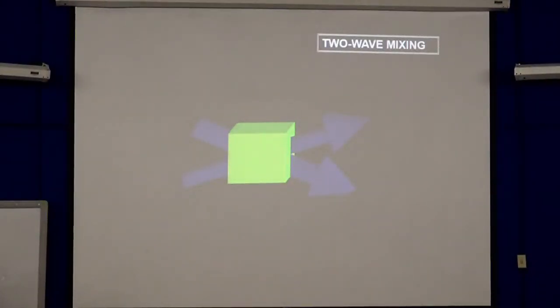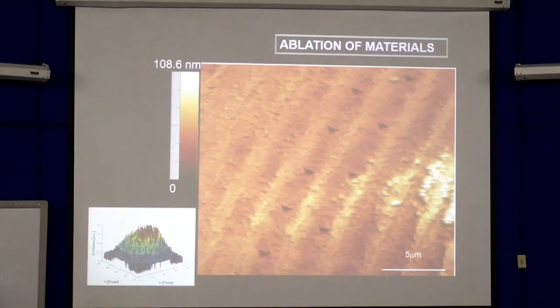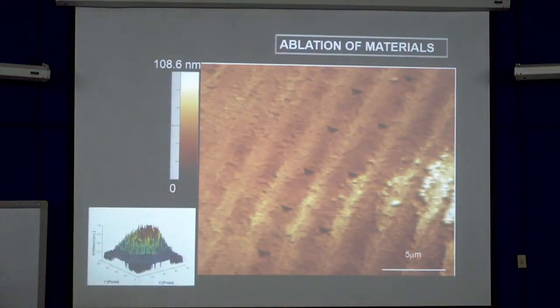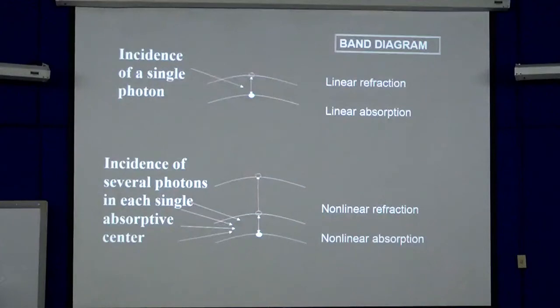So now the two-wave mixing experiment. If we make an interaction of different beams with the same wavelength and the same polarization, in the superposition of the two beams we have an interference pattern. If we produce this superposition, it's possible to make this kind of damage. The lines are related to the period of the wavelength that you use for the incidence. But if, instead of using a material that absorbs the light strongly, you use a semi-transparent material, there is a possibility for linear refraction, linear absorption.